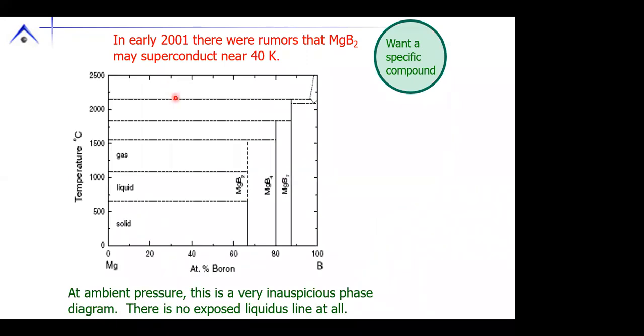All right. In 2001, there were rumors that MgB2 may superconduct near 40 Kelvin. Now, this was beautiful, but when we go to the binary phase diagram, we see that there is no simple way of growing single crystals of MgB2 from the binary. There is no liquidus line that we can access. You essentially immediately precipitate out fine polycrystals.